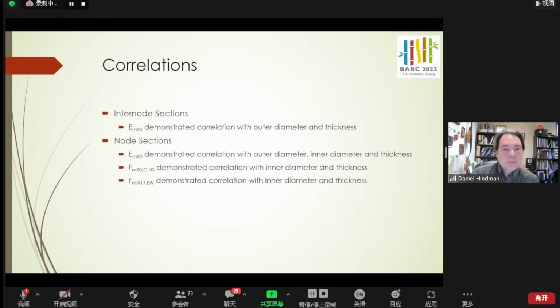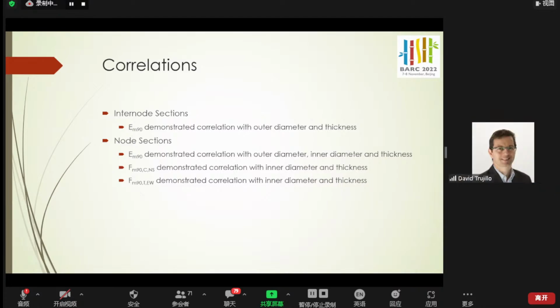Then finally, we tried to do some correlations of the different strength and stiffness values with the dimensions of the individual rings. So we used the outer diameter, inner diameter, and thickness, and these were the correlations we found meaningful. For the internode, the stiffness was correlated with outer diameter and thickness. For the nodes, the stiffness was correlated with outer diameter, inner diameter, and thickness. And then the compressive stress in the north-south and the tension stress in the east-west were both correlated with the inner diameter and thickness.